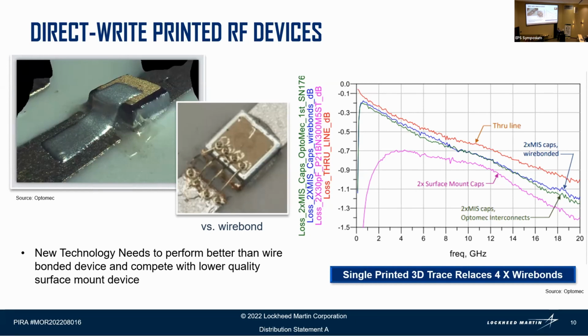So we've got to show performance improvement, and that's what you're seeing here. Compared to a surface mount cap, this performs better. Compared to a wire bond, it's relatively the same, as you can see. But the benefit is that when we built this one, it was done in a clean room, usually in a hybrid-like device. We're hoping to actually integrate this onto just a standard circuit card. So removing that extra step in the process is a huge benefit to using this technology.